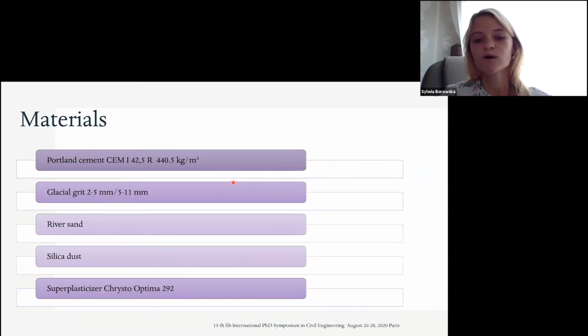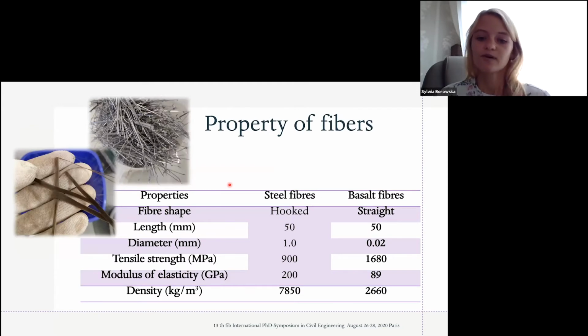For research concretes, Portland cement CEM I 42.5 R was used in the amount of 440.5 kilograms per cubic meter. The maximum grain size of the aggregate was 11 millimeters. River sand of 0 to 2 millimeters grain size was applied. The properties of fibers implemented in high-strength concrete are as follows. Hooked steel fibers and straight basalt fibers, 50 millimeters long.